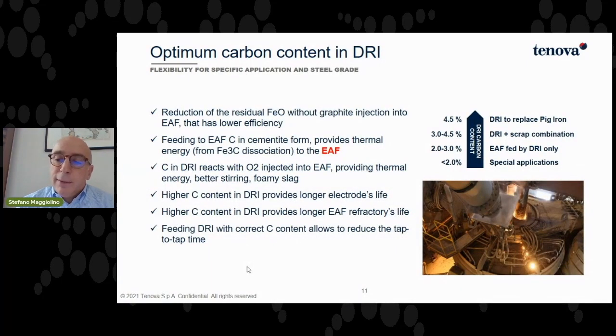We have decades of experience producing different qualities of DRI, with carbon content ranging from lower than 2% for special applications up to 4.5% when the DRI is used to replace pig iron. We have total flexibility to set the requested carbon content in the DRI, with benefits that we see in the end user, that is the electric arc furnace.